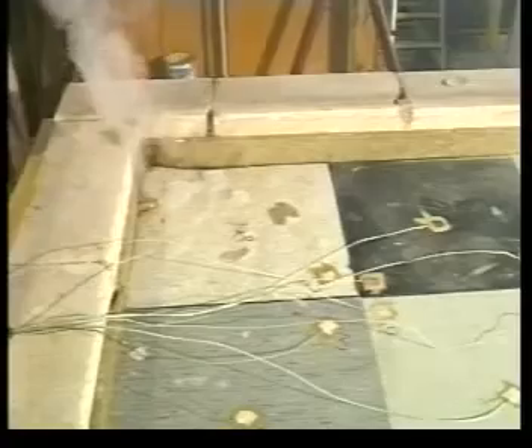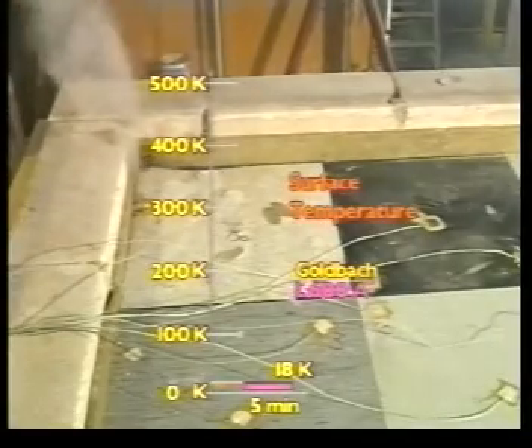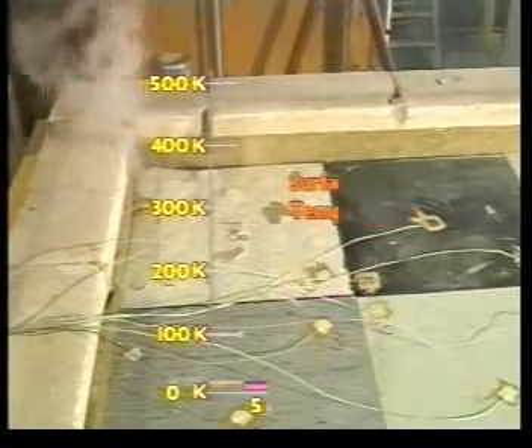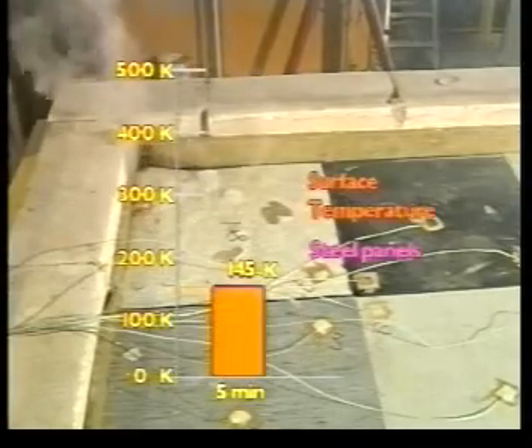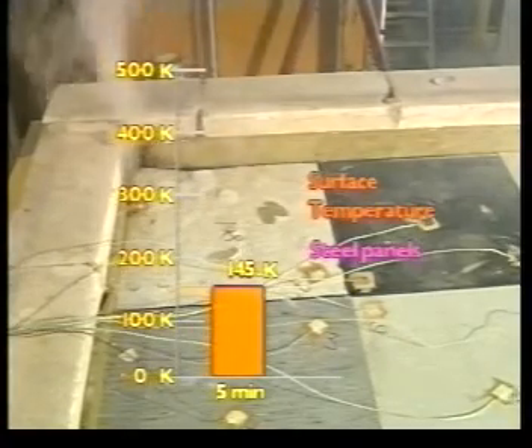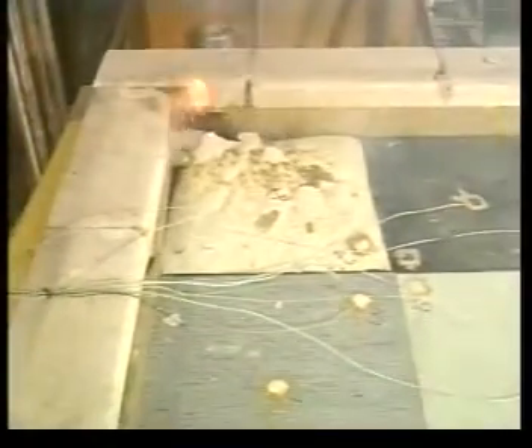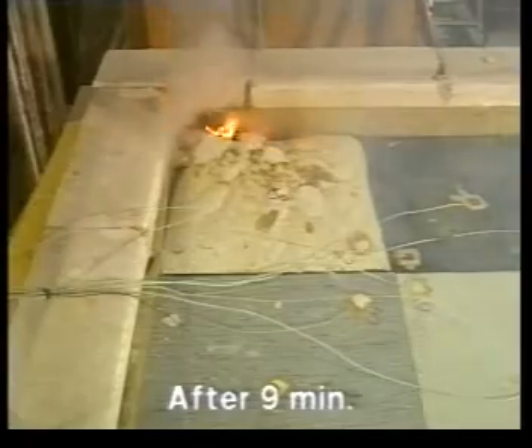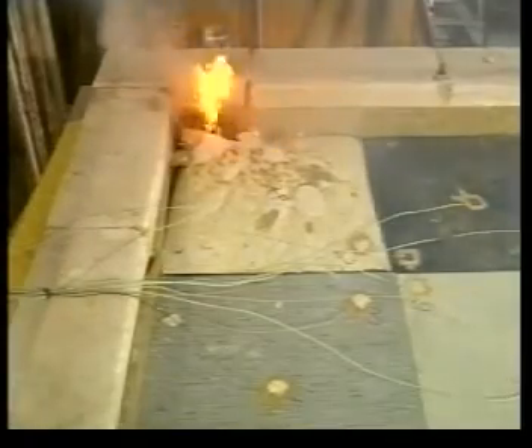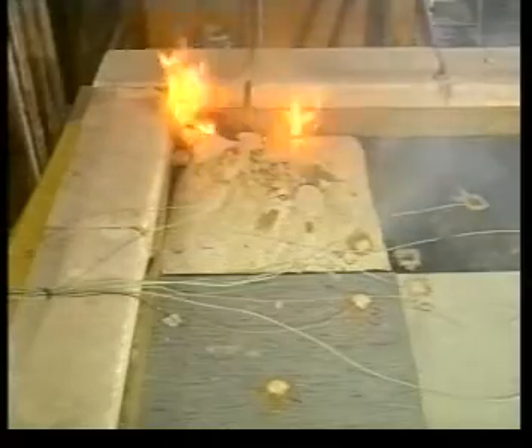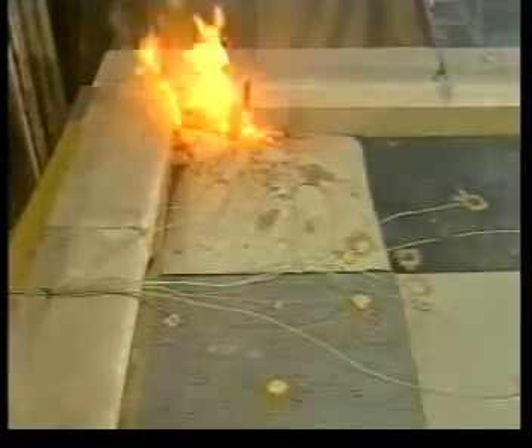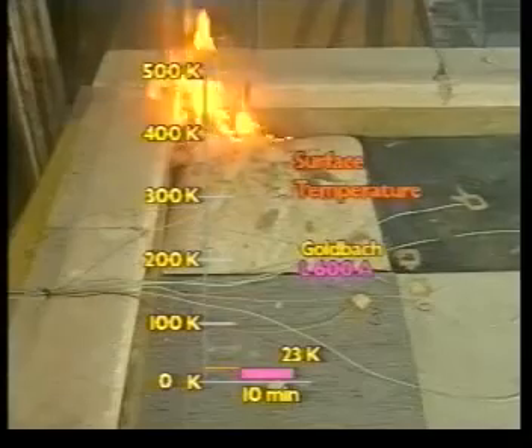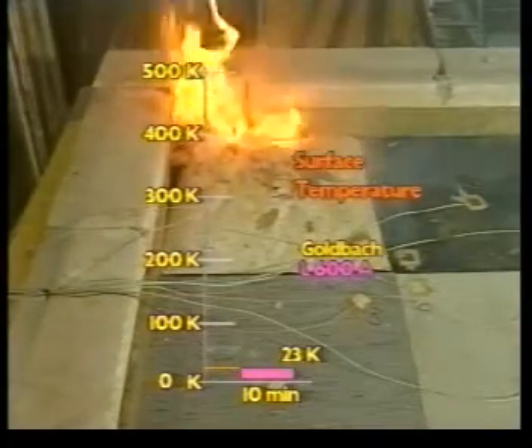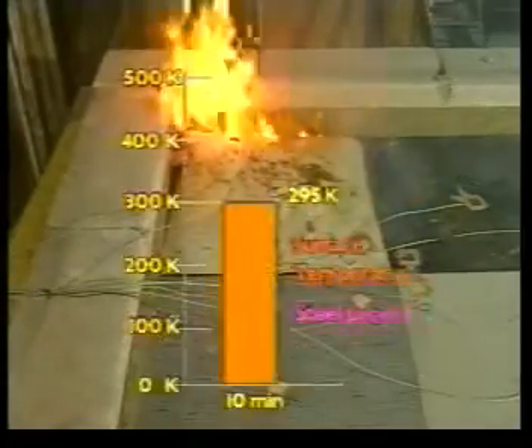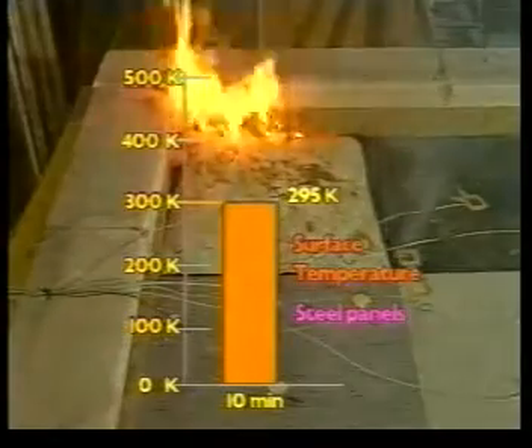After 5 minutes, the increase in the surface temperature of the Goldbach panels amounted to 18 Kelvin. The surface temperature of the steel panels, on the other hand, amounted to 145 Kelvin. After 9 minutes, the HPL coating of the steel panels caught fire. The surface temperature was registered as 280 Kelvin. After 10 minutes, the surface temperature of the Goldbach panels was 23 Kelvin. But the surface temperature of the steel panels was 295 Kelvin.